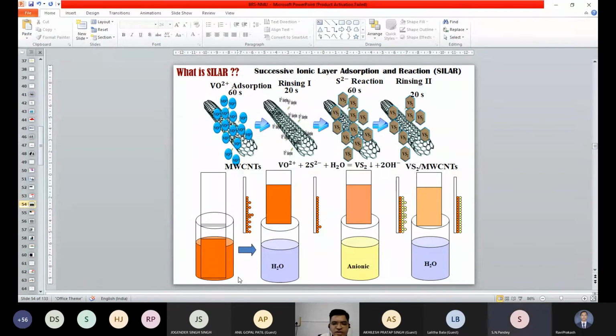Okay. So here, one solution is cationic and another one is anionic. For the vanadium, we have used vanadium in the 2+ state. If you have the substrate with the carbon nanotube, we dip it inside the cationic solution so that the vanadium ion gets adsorbed on the carbon nanotube. Then we rinse it inside ion exchange water, so whatever unadsorbed ions are there can be removed.